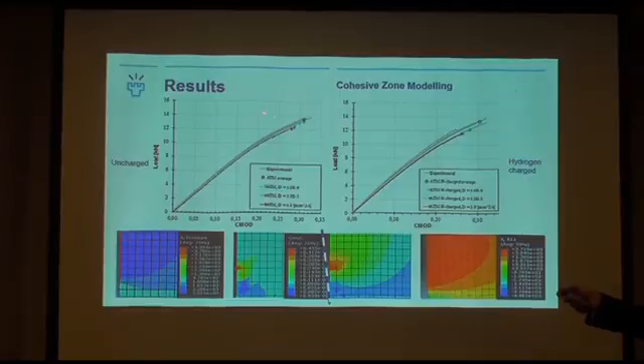And when we insert more hydrogen into the model, we actually expect even lower toughness values than what was observed in our experimental tests. And we also enhanced the diffusion rate to model slower displacement rates. And then we see an even further additional decrease in toughness, so from this point to here, and from here to here, and that can be explained by the findings that the hydrogen population is more in line with the hydrostatic stress state, with sufficient time for it to accumulate there in larger quantities.